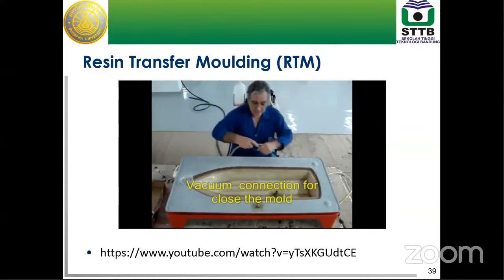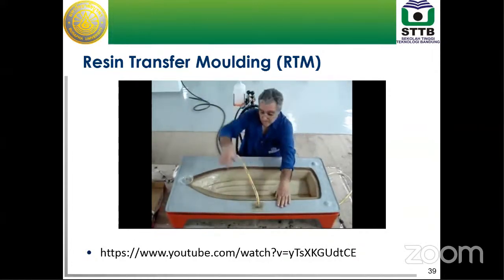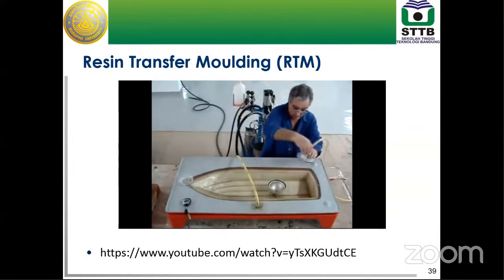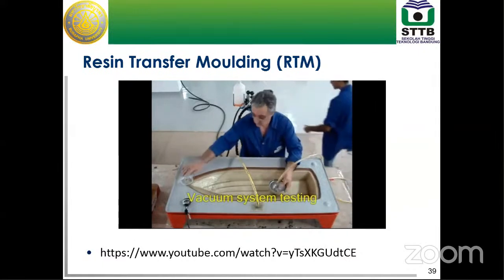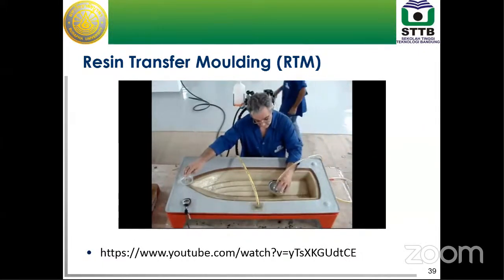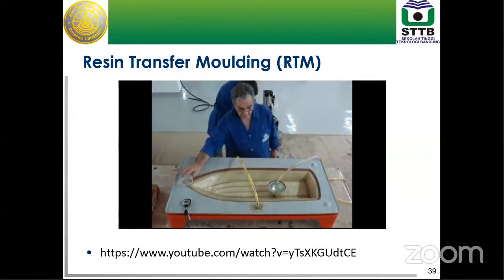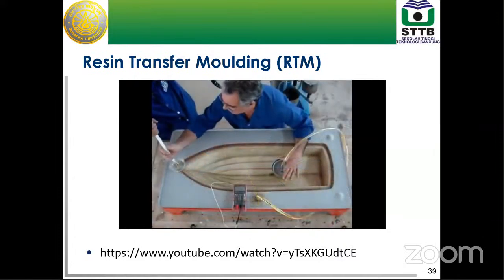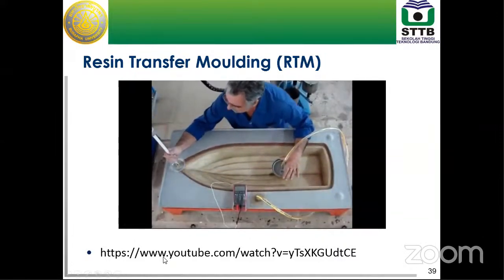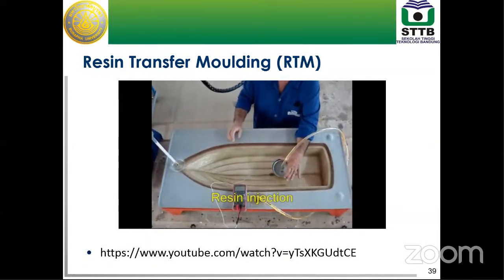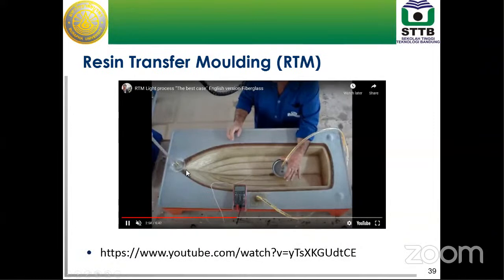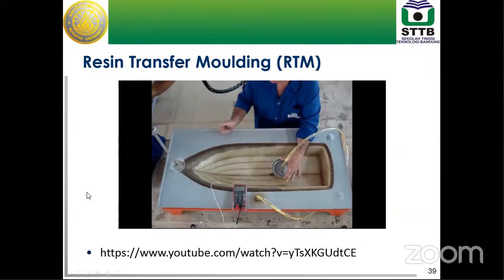Vacuum. So the pump is connected at one extremity to create the vacuum. And they test. This is a leak test. I mentioned the leak test before. They check if the pressure is well applied everywhere. And now they will connect the resin injection. And you see the resin come up. The vacuum pulls the resin through the fiber. So you see the color? With a glass fiber, it's easy to see. So we have the resin moving through the shape of this boat.